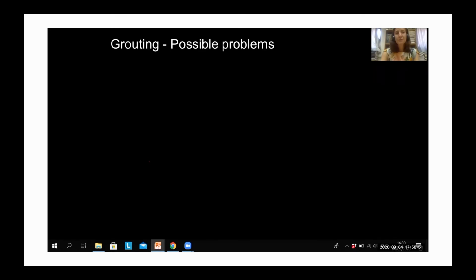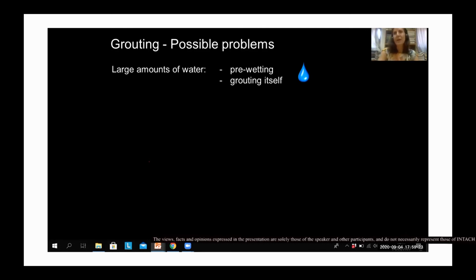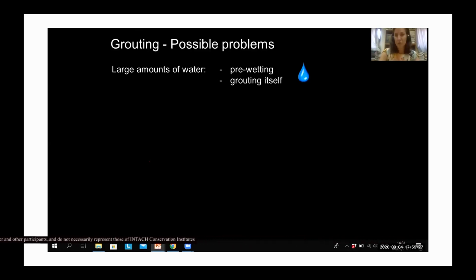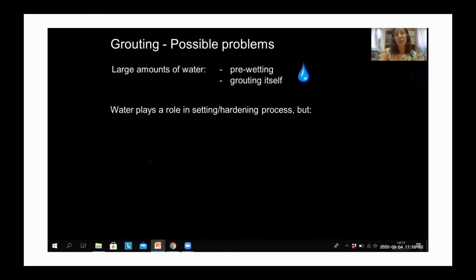So in terms of complexity of the intervention and possible problems which grouting can lead to, as we saw, the typical suspension medium of grouts is water. In general, the whole intervention involves a large amount of water, typically, because before injecting the grout, pre-wetting is usually performed. So the pocket is pre-wetted with water or water and alcohol in order to prepare the surface so that the plaster doesn't absorb immediately all the suspension medium of the grout, which would shrink immediately. And then, of course, a lot of water comes in with the grouting itself because it's the main component in terms of amount of the grout. And so we do know that water plays a role in the setting and hardening process, in the chemical reactions.